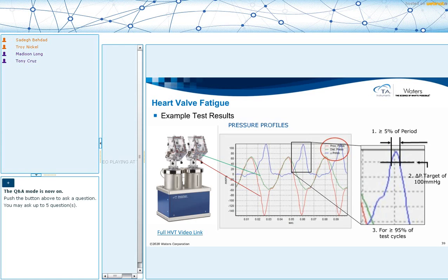So here is a zoom in of that pressure differential. The three things that we want to look at: that the delta pressure is above 100 millimeters mercury for 5% of each cycle. And the third aspect would be over several million cycles, you have to make sure that for at least 95% of those, you are maintaining that pressure differential.